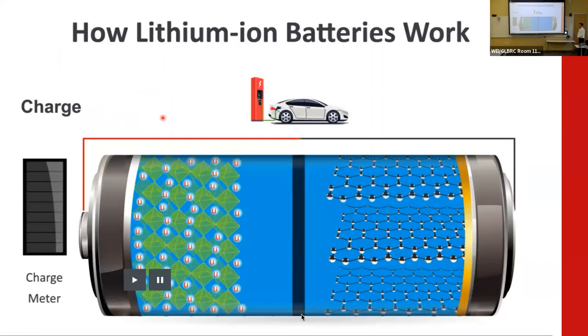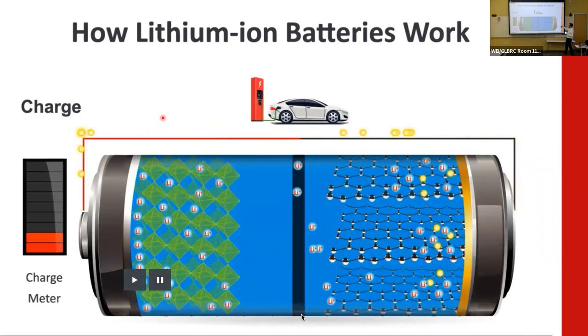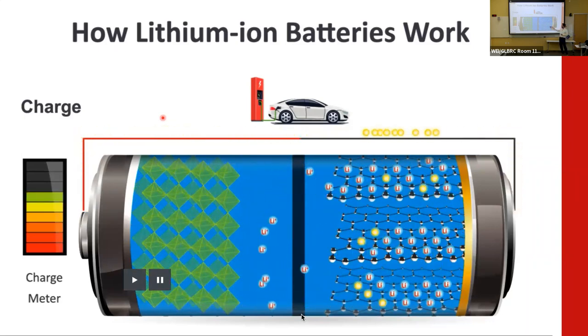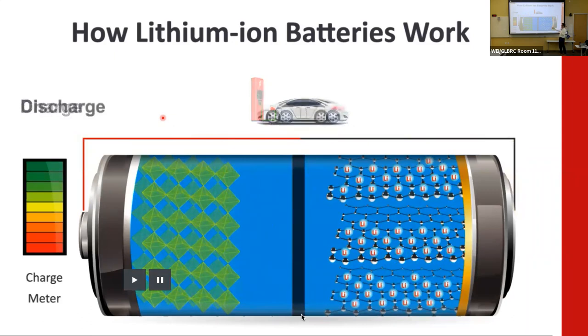In a lithium-ion battery, similarly, we have two reservoirs. In this case, they're reservoirs for lithium. So on the left side here, those green tetrahedra are a crystal structure of a metal oxide. And you can have lithium in that crystal structure, and it's nice and happy because it's got oxygen around it. Lithium really doesn't like to be in the metallic state, so it's nice and satisfied with its oxygen. But if we apply an external voltage, we can drive electrons through the external circuit, and that forces lithium ions across the cell. So as this plays, you see electrons going through the external circuit, lithium ions going through the middle, across an ionically conductive electrolyte, and reuniting with the electrons over here.